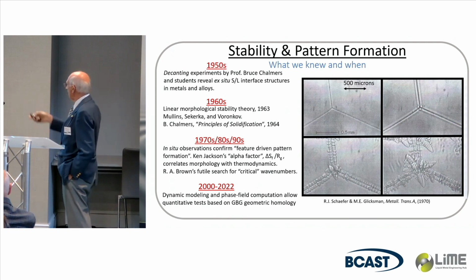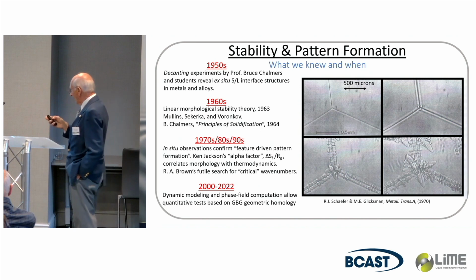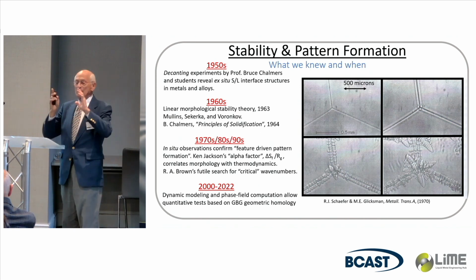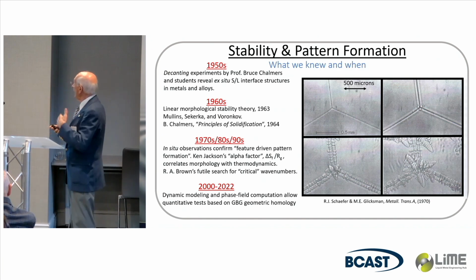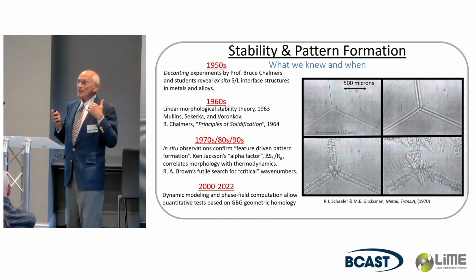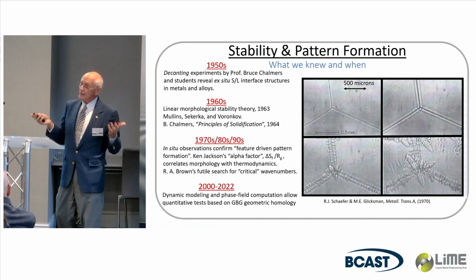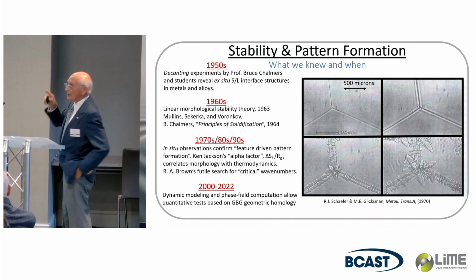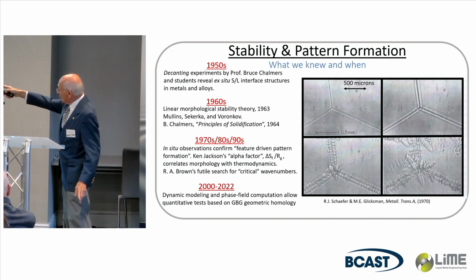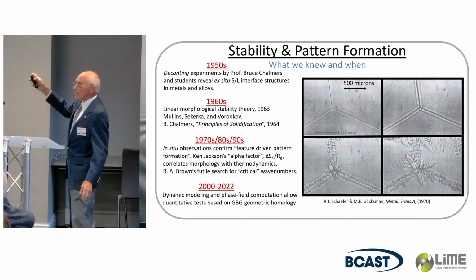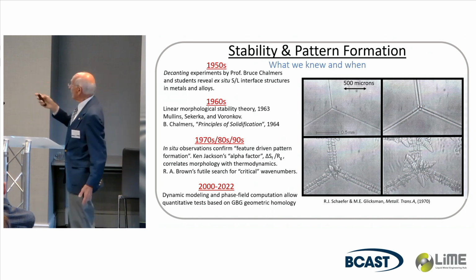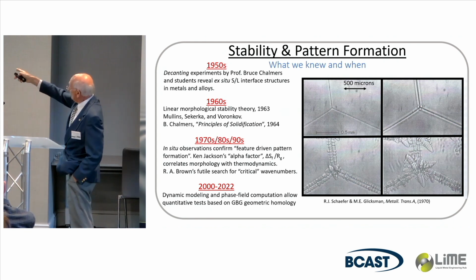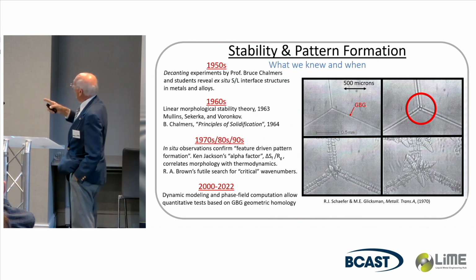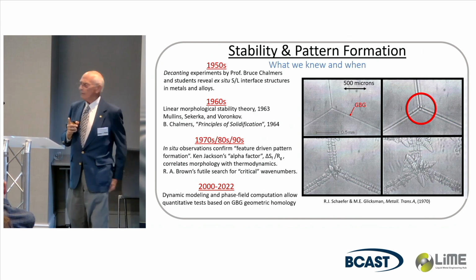In work that I published with Bob Schaefer back in 1970, we finally did what we call in situ observation. And I just pulled these out to show you why these observations did not really coordinate with linear morphological stability. So we're looking through a transparent melt, and we picked the substance through the Jackson alpha factor. This happens to be a body-centered cubic material, but it's got a transparent melt, and we're looking down at the plan view of a solid-liquid interface with 3 grains intersecting with a grain boundary groove. And that groove is about 20 microns wide.